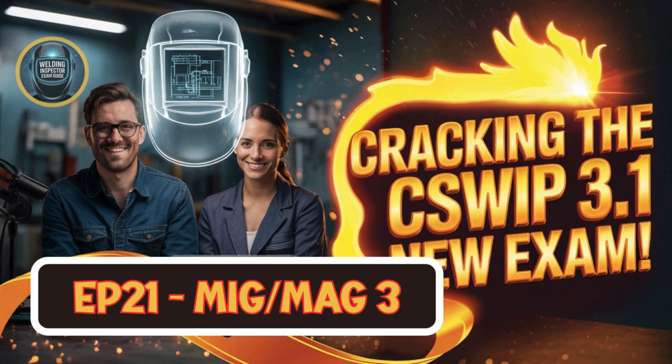Wow, 85% helium. So we're talking incredibly specific blends tailored to the material. Absolutely. And for light alloys, aluminum, magnesium, titanium, copper, nickel, those argon-helium mixtures are often indispensable. Because of the heat again. Exactly. Helium's higher thermal conductivity gives you a hotter weld pool. That means better penetration, or you can weld faster. Sounds like a win-win. Any downsides? There are trade-offs. High helium content gives deep, broad penetration, which is great, but it also tends to increase spatter.